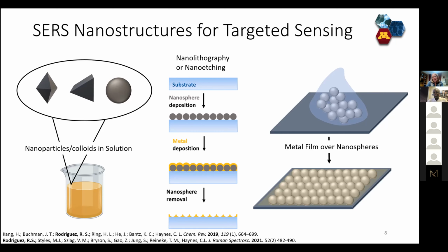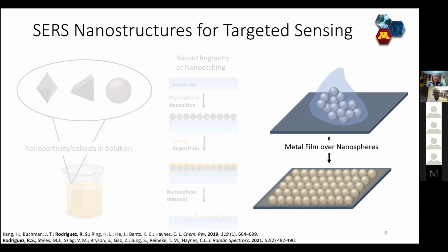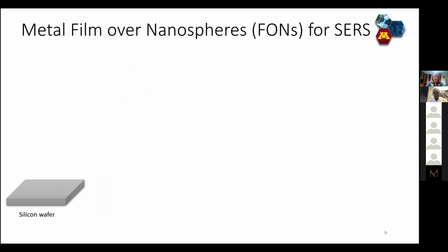Or on the far right-hand side is a substrate that I'm going to focus on today, a really simple SERS substrate called a metal film over nanosphere. So let me show you all the steps of making these. It's actually pretty easy. You start with a flat substrate. We use silicon, glass, mica, copper. You can use copper if you need something conductive, for example, and then we can actually buy a nanosphere suspension. These nanospheres are hundreds of nanometers, and you can commonly get them made out of polystyrene or silica. You want the most size monodisperse colloids that you can get because they self-assemble into a close-packed lattice.